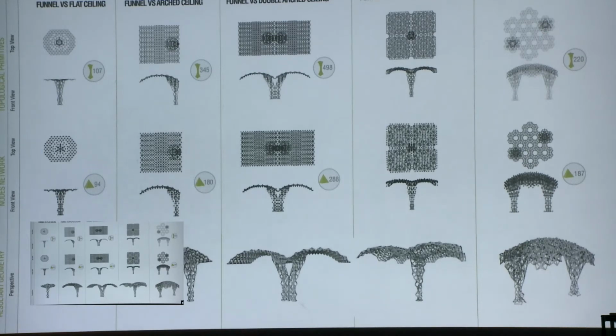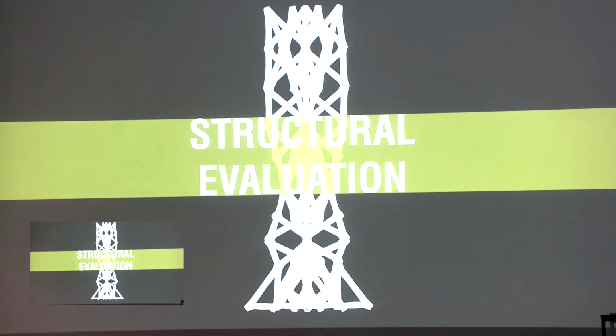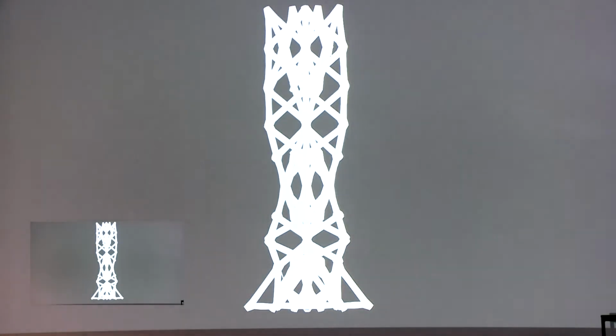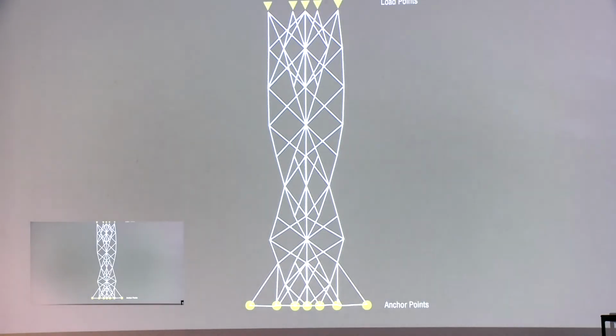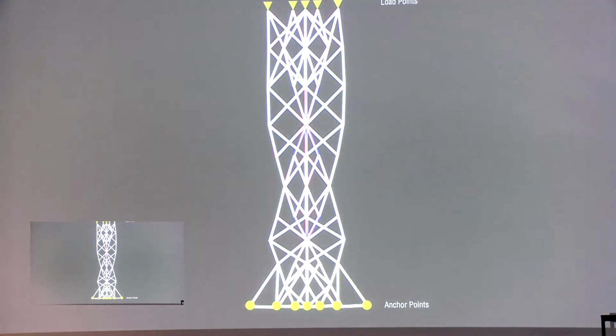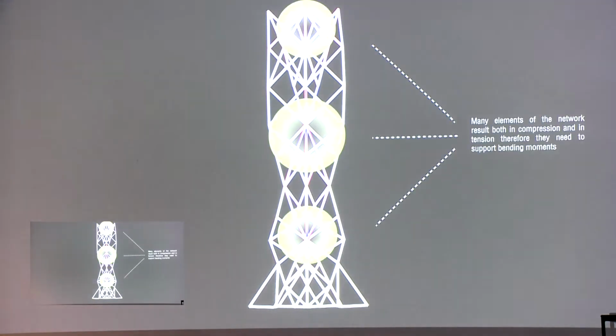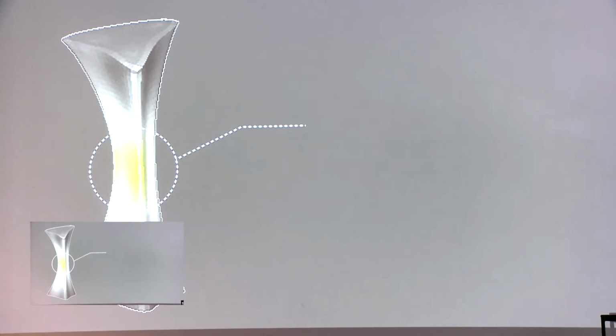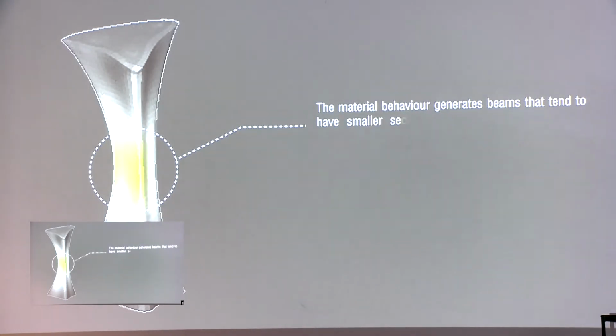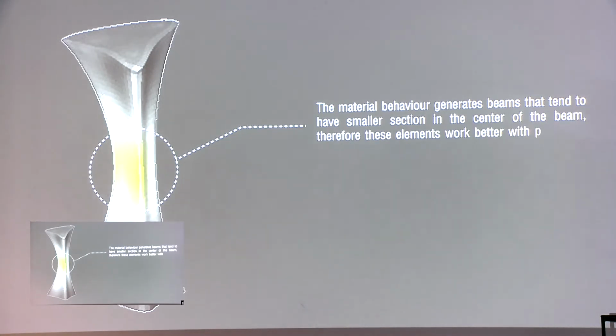These special primitives are evaluated from a structural point of view for the requirements given by our material. Thanks to the structural analysis, we understood that some of the elements in our lattice are both in tension and in compression. But we observed that the material that we have generates beams that are thin in the center, so they are unstable and work better in pure axial forces, either tension or compression.